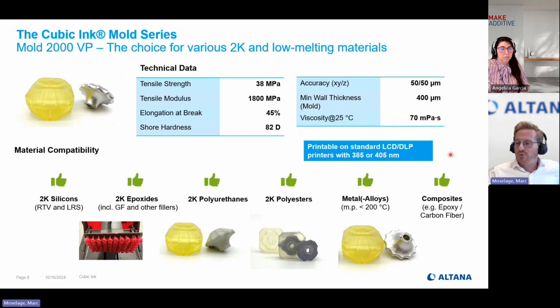And additionally, also composite materials. Specialty resins called prepreg resins, consisting of an epoxy matrix and a carbon fiber, work pretty well. And if you have other materials which you do not find here on the list, it's very likely we haven't tested them yet. It's not because they don't work. So in the end, most of the materials shown here work. Very likely some others will also work. Most of them work without an additional cast separator. And if a cast separator is necessary for a certain application, we can also deliver one.